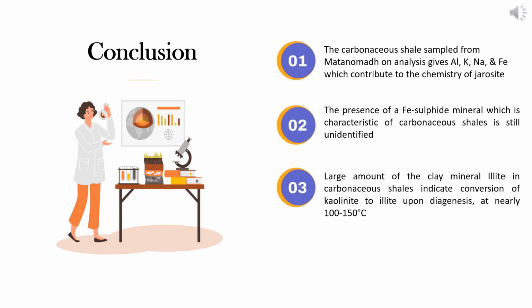2. The presence of an iron sulfide mineral which is characteristic of carbonaceous shales is still unidentified. None of the peaks exactly correlate with any iron sulfide mineral diffractograms. 3. Large amounts of the clay mineral illite in carbonaceous shales indicate conversion of kaolinite to illite upon diagenesis.